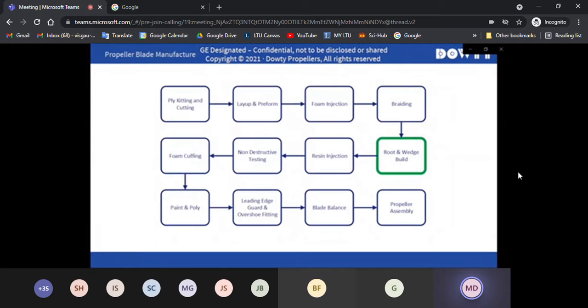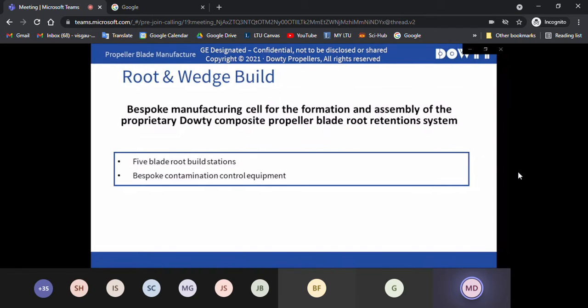At this point, the dry carbon fiber preform is almost ready for resin injection to make the final composite blade. We just need to add a few finishing touches and also to attach the metal root fitting onto the blade, which provides the structural retention of the propeller blade when it's rotating to the hub. We call this operation build.